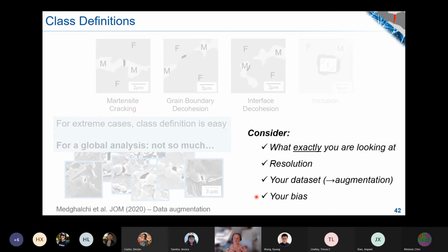If you want to do this kind of work, what we found is that you need to define exactly what you're looking at. We wanted to look at the underlying mechanisms. Actually, the classification task that we ended up giving the algorithm is to look at the underlying mechanism for freshly nucleated sites, because our brains tend to infer what we think happened, but a crack that's just nucleated and a crack that's opened up and deformed the surrounding ferrite look very different. So you have to define very well what you're looking at.